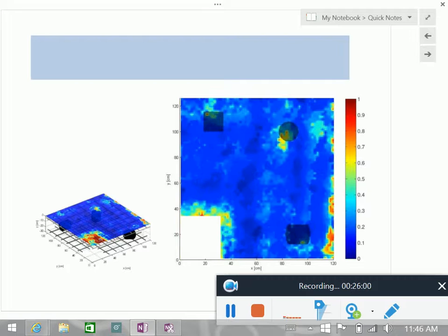So you have to avoid this kind of edge area. That's what I said, that it doesn't have a good spatial resolution, because it affects a volume around it. So if you go towards the edge, you get artifacts. There is no perfect method for anything. For every method, you have to understand what it does and be able to interpret it.